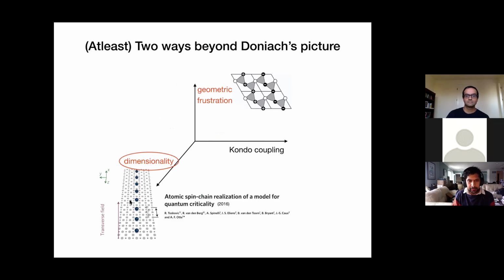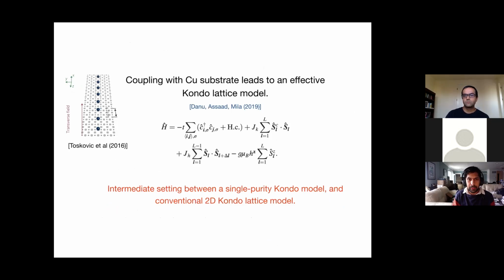Anyway, the next part I want to mention is this dimensionality effect of going beyond the Doniach phase diagram. This is the kind of experiment, cobalt atoms on some copper metal, and this is very similar to this recent work done at Stanford also. There's a fairly detailed modeling of this experiment. All the features were reproduced by a Kondo lattice model, where conduction electrons are the copper ones, and spins are effective spin 1/2. Cobalt is spin 3/2, but because of the anisotropy, it becomes effective 1/2 once you take into account the Jahn-Teller kind of effect. Then the coupling is just Kondo coupling, and we don't add magnetic field in our paper, but this is the kind of model we want to study.